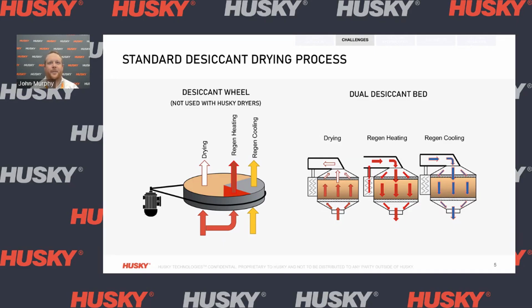Currently, the industry is dominated by desiccant technology. This technology is typically in the form of desiccant wheel or dual desiccant bed. For desiccant wheel technology, a wheel is rotated for continuous drying capability. The majority of the wheel is dedicated to process air being dried as it flows through the wheel. There is a small section of the wheel dedicated to regeneration heating and regeneration cooling. As the wheel rotates, the regeneration process is able to remove moisture from the wheel to make this a continuous process.